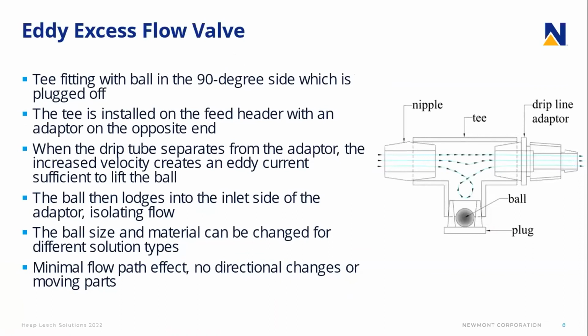The next excess flow valve that we created was the Eddy EFV. This one is a T fitting with a ball in the 90-degree side, which is plugged off. So it's a PVC T. What we were using was 1/2-inch adapters and 1/2-inch fittings. So that's what we started with. The ball rests down in the plugged side on the bottom side of the T. The T is screwed into the feed header with a nipple, and then the adapter is on the straight side of the T on the opposite end.